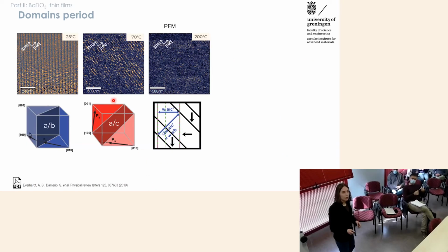So here you can see how the two phases look in the piezo response force microscopy. This would be the room temperature phase, which is AB, and the domains here are aligned along the 110 direction at 35 degrees. And when we warm up across the phase transition, we switch to the in-plane, out-of-plane phase. And now the domain walls are at 45 degrees with respect to the domains of the other phase. So we see a tilt in these domains. And of course, if we go above the ferroelectric phase transition, then the apparent contrast disappears.